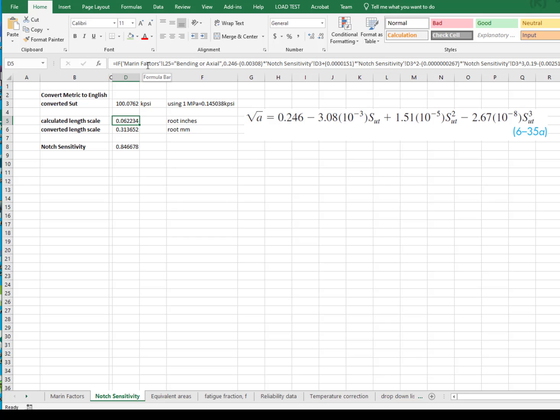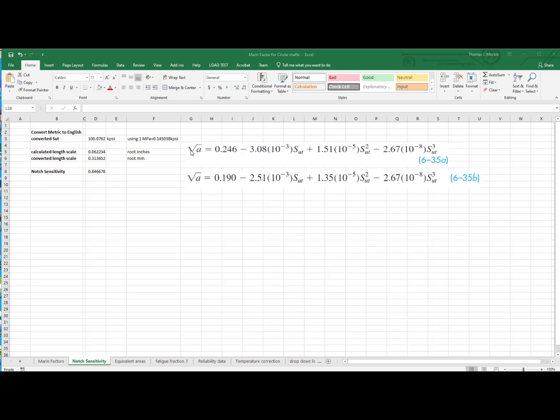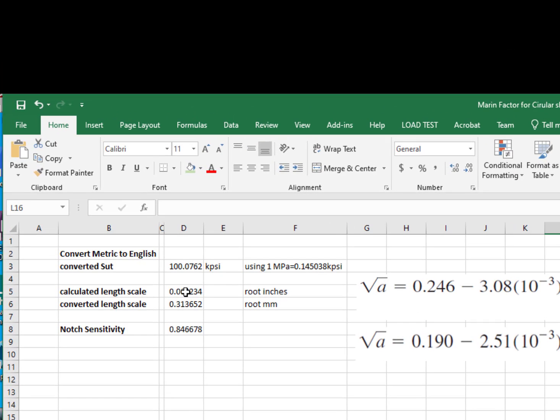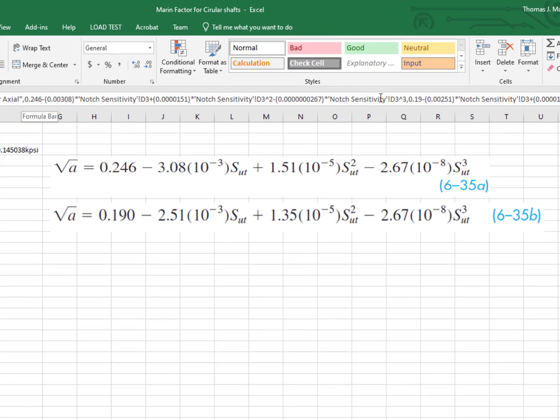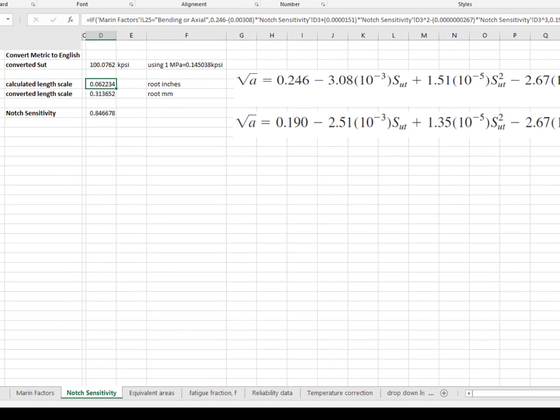Well, the first thing I have to do, though, is check whether or not I have bending or axial loading. Because if I do not have bending or axial loading, then I have to use a different Neuber length scale equation. Okay, so the two length scale equations: if we have axial or bending loads, we use equation 635a. And if we have torsional loads, we use equation 635b. So when I calculate my Neuber length scale, I have to have a check statement to decide whether I have bending or axial loading. If I have bending or axial, I use this equation, which I've reproduced here. Ugly in Excel. Otherwise, I use this equation, which I've also reproduced in the Excel spreadsheet.